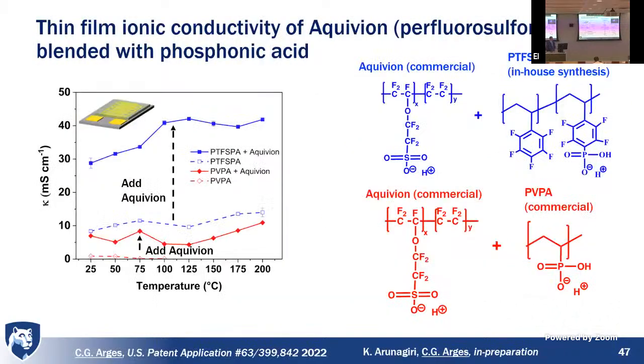So my other student, Kartik, is studying this. And we looked at a different perfluorosulfonic acid material that's analogous to Nafion called Aquivion. And we can take this PTFS-PA, this phosphonic acid, and mix these two. And when we add the Aquivion, this conductivity here jumps up. So you do get higher conductivity with Aquivion. This is on a thin film, which I showed earlier. But this one we have to make in the lab. Like we have to polymerize the monomers, and we have to functionalize it.